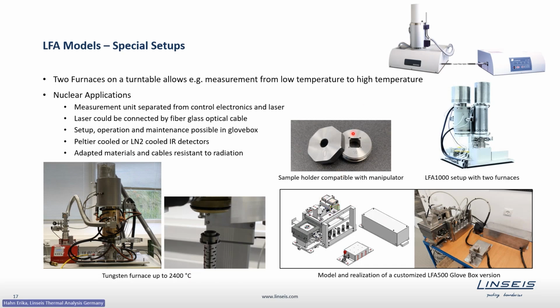And also the sample holder can be adapted to such glove box applications. Here we made sure that the sample holder can be handled also with a manipulator, so with a robot. In general, what might also be advantageous for such applications is that we offer different detectors, a Peltier-cooled one and a liquid nitrogen one. Peltier-cooled means that the detector is thermoelectrically cooled, so there is no need to have liquid nitrogen. In general, we typically recommend the liquid nitrogen cooled detector as it is the more stable and more precise one.